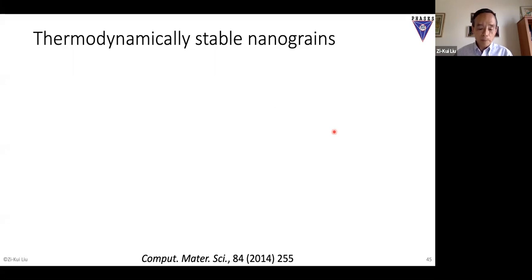That's very interesting because we all know grain boundaries have segregation, elements can segregate to the grain boundary. But we never talk about whether that segregation reduces the grain boundary energy, or reduces the boundary energy of the system compared to single crystal. This was in the 1990s, when people started making nanomaterials. Some German scientists thought, if I make the grain so small, and you have enough segregation, actually the nano grain is more stable than the single crystal.